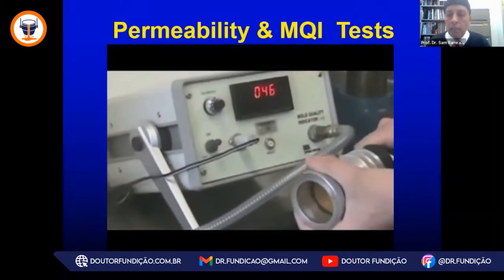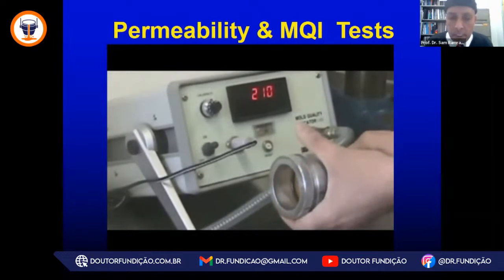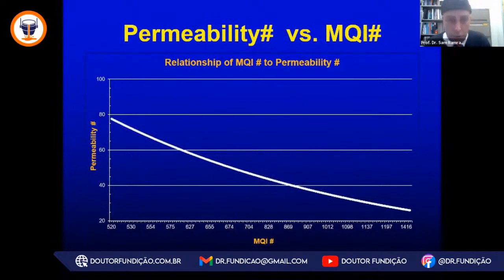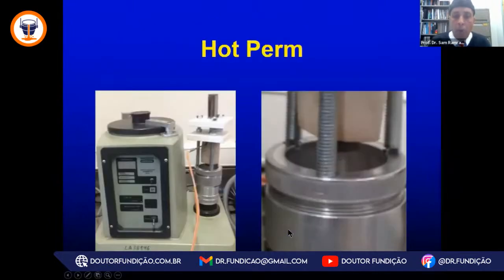And then we can run the mold quality index test using the same specimen holder. And that shows an inverse relationship between the permeability number and the MQI. They are related. But more importantly is running that test hot. Why that is important is because, again, the dynamic properties of green sand during the casting process is where the magic happens. That sand, when it gets hot, the binder bridges change, they soften, they collapse, or they vaporize. And because of that, the permeability number during a hot experience at the mold metal interface is a more important value for our advanced engineering tools and understanding the venting characteristics there.